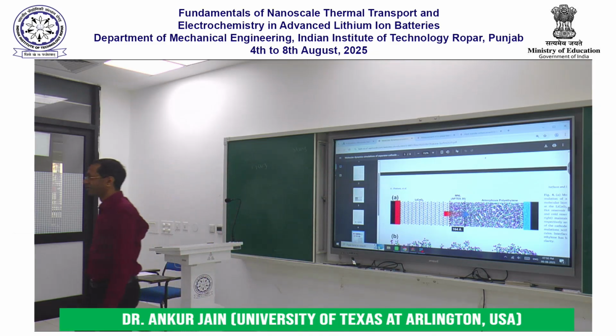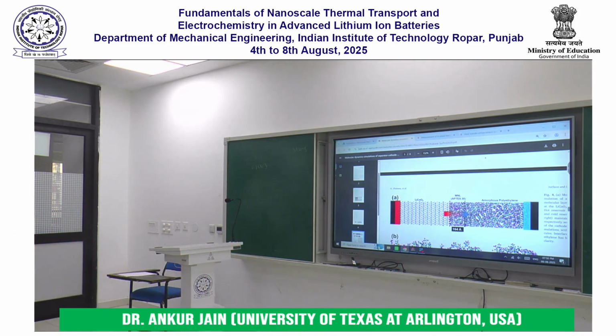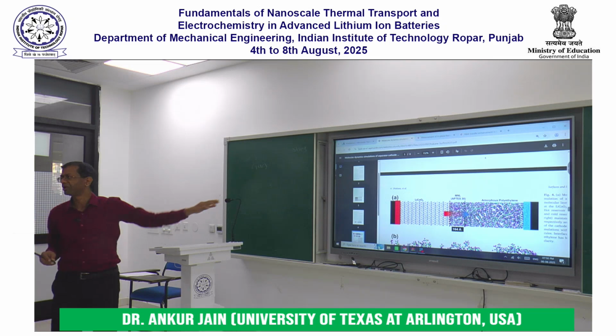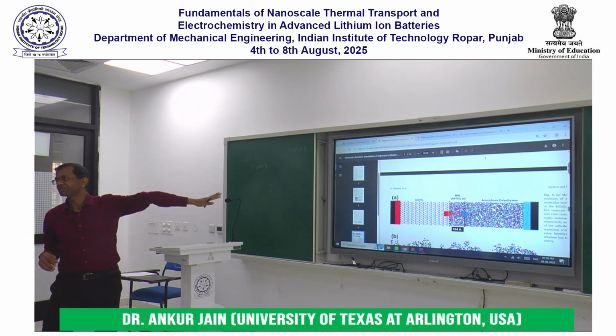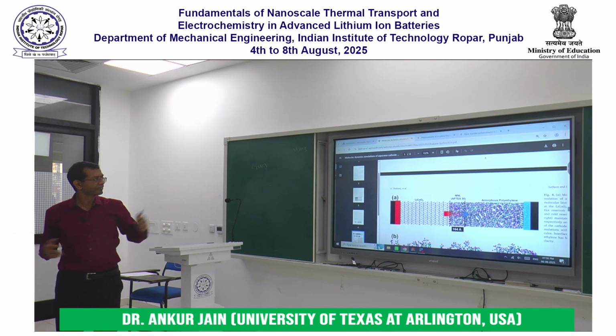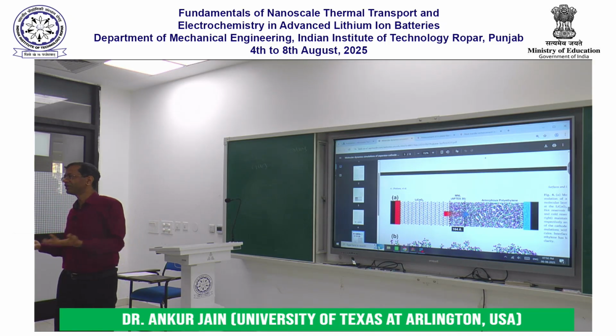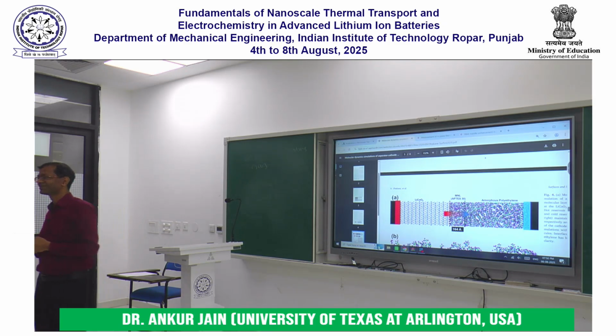What properties or variables are required for the simulation? The variables required here are not thermal conductivity, heat capacity, density, etc. Those are bulk values. The properties needed here are the intermolecular potential force field, Lennard-Jones force field, something like that, of these molecules. You can see I'm not an expert here, but if you don't know something, what do you do? You go and talk to people who know. And if one of them turns out to be your batchmate, that really helps.